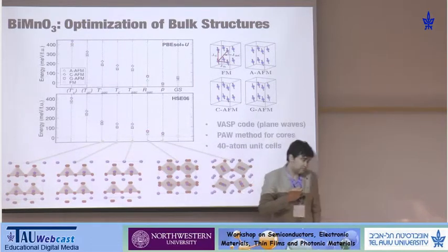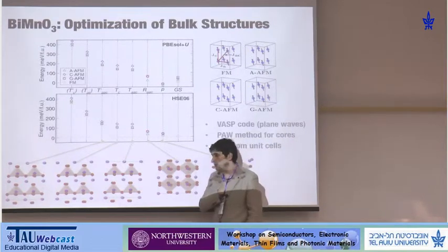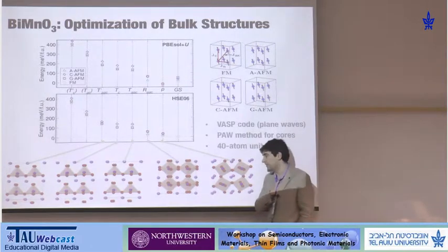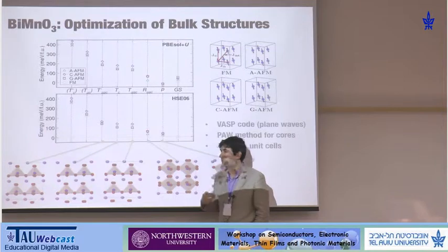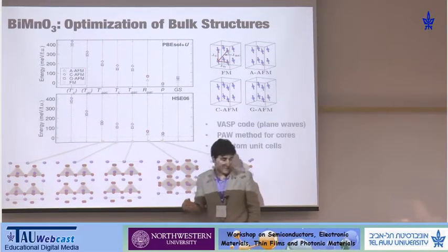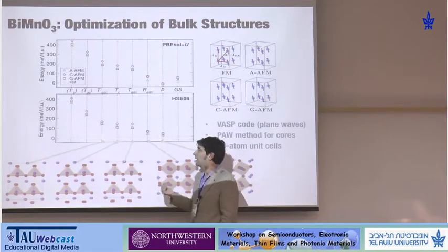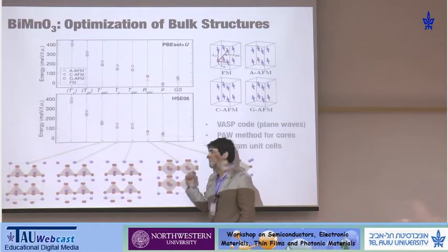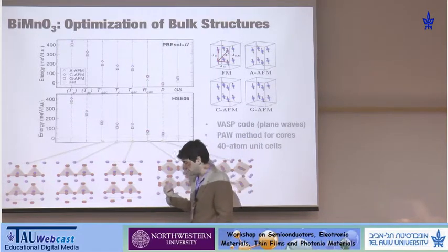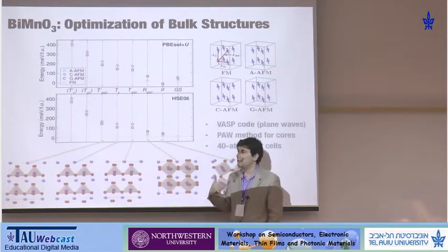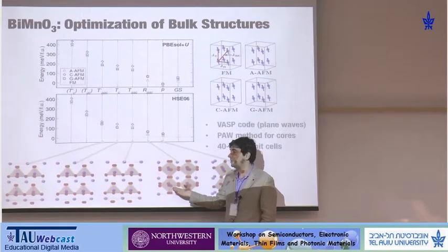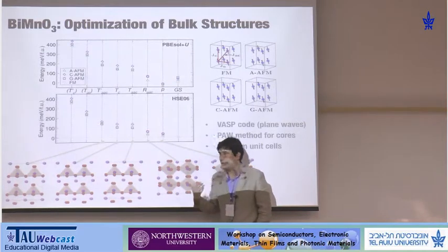In density functional theory, which I didn't say anything about before, you always make one approximation regarding what is called the exchange and correlation potential. It's known that the energy is a functional of the electron density, but it's not known what the expression of the functional is, so you need an approximation. Many times you use the local density approximation or the generalized gradient approximation, and it works. One kind of materials where it's known that it does not work is materials with transition metal atoms like these ones, where the electrons are highly localized. The typical density functional theory implementations fail to localize these electrons because of the way they are constructed. So in many cases, what should be a robust insulator like this with a 2 eV gap comes out as a metal.